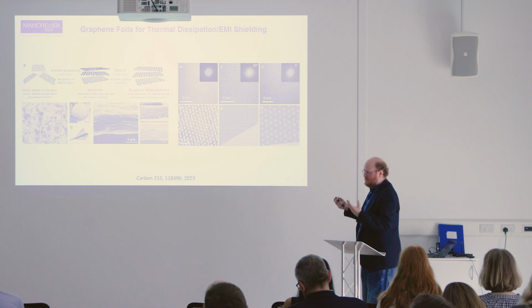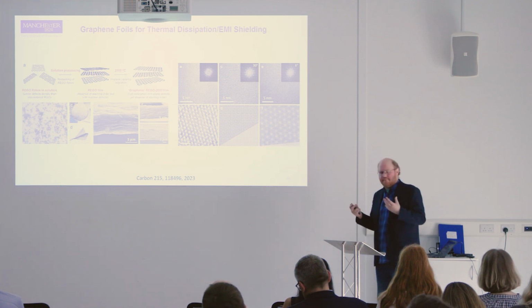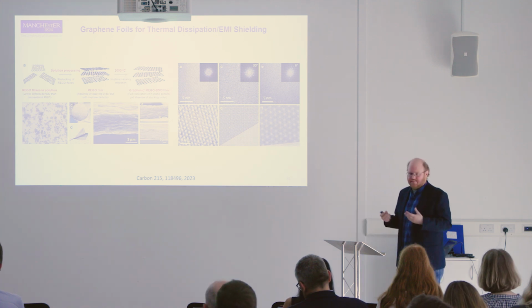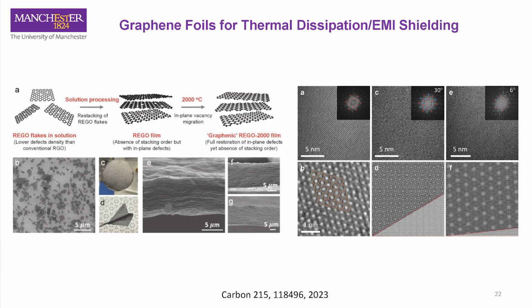You can also do this with graphene. This has been done by companies like Huawei, who had a phone that was doing this, making these basically graphene heat spreaders. So traditional mobile phones and laptops use graphite as a heat spreader. And often people say, well, what's the difference between if I have graphite or I take graphene and restack it? Why would that behave any differently? And it really all comes down to the stacking interaction.